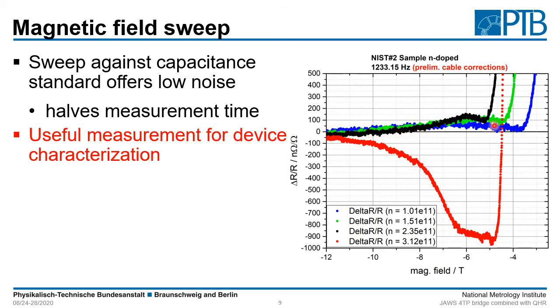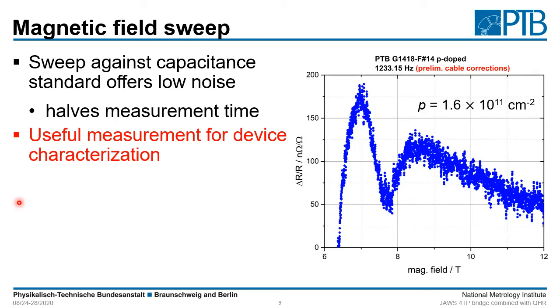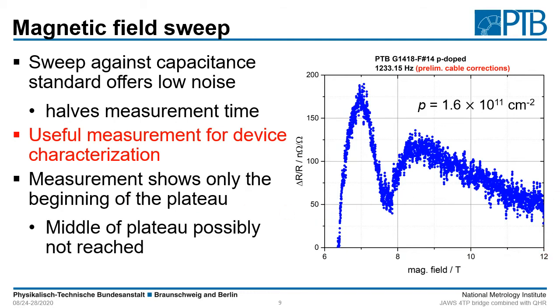You can see that the carrier density also influences the shape of the magnetic field response of the quantum hall device. The same measurement was also made for the PTB sample, which is P-doped, showing quite similar behavior but at the opposite field sign. Unfortunately all our measurements do not show precisely the middle or both sides of the plateau. We can only look at the first part of the plateau, and therefore we cannot be sure that at 12 Tesla, our maximum field, we already reach the middle of the plateau. Please keep this in mind for all upcoming measurements.